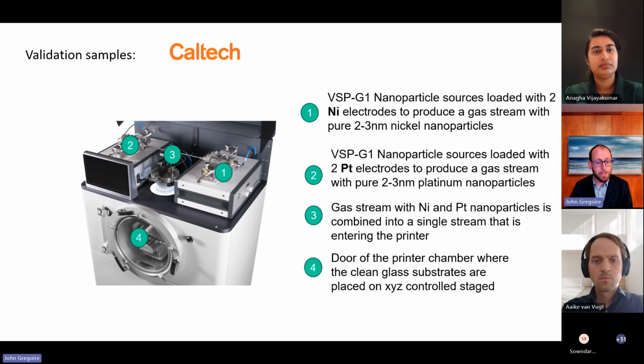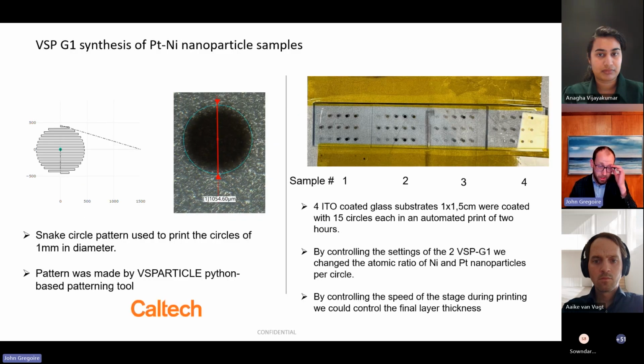We had a collaboration earlier this year that I'll show you a few slides of before turning it over to Aaike to tell you about this in much greater detail. This has a platinum source and a nickel source, mixing them together so we can print mixed nickel platinum nanoparticles on an ITO coated glass plate, very similar to the inkjet printing glass that I showed you before. This is done by controlling the power in the two elemental generators of nickel and platinum to control the composition, and then rastering a beam of nanoparticles depositing onto our substrate.